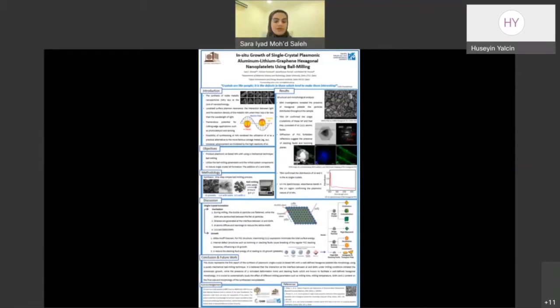Now, research has primarily focused on the synthesis of gold and silver nanoparticles because of their relative ease of synthesis. However, these metals have limitations, including their high cost. Recently, aluminum has gained significant interest as a promising practical alternative to the coinage metals gold and silver. This is because it is far more abundant, it has a lower cost, and most importantly, it has a higher density of free electrons, which means a higher plasmon frequency and better optical performance. However, the problem faced with aluminum is its high reactivity, which renders the synthesis of aluminum nanoparticles using the well-developed chemical synthesis techniques challenging.